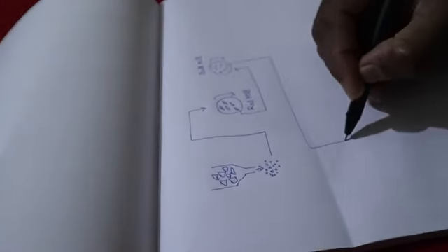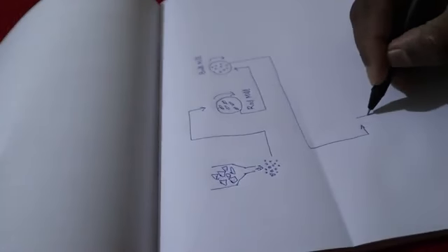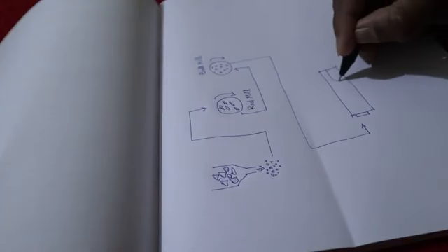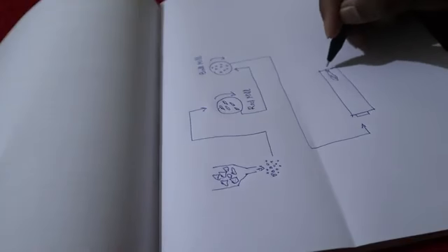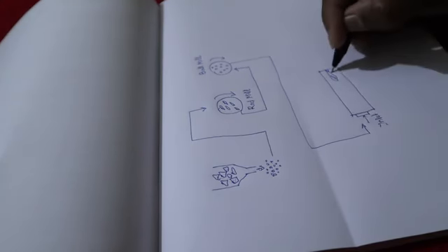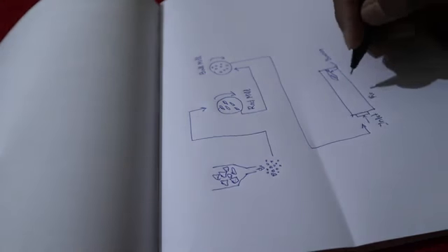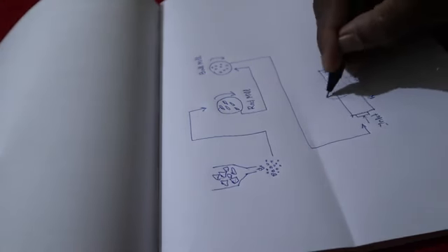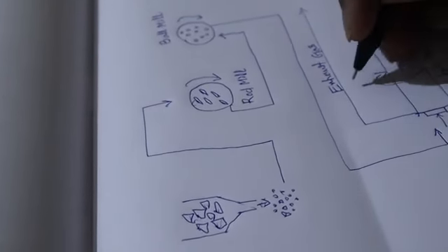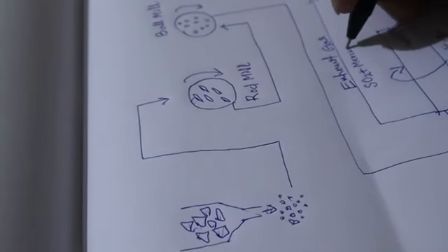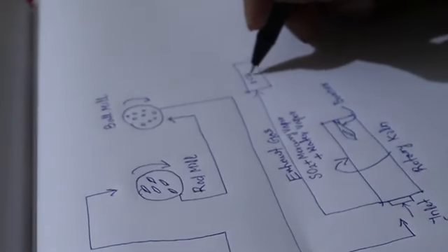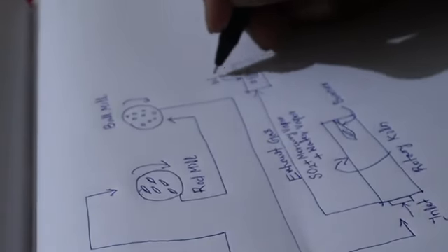Once the ore is finely powdered, it is fed into a furnace or kiln to be heated. The heated cinnabar reacts with oxygen in the air to produce sulfur dioxide, allowing the mercury to rise as vapor. This process is called roasting. The mercury vapor rises through the exhaust along with sulfur dioxide and water vapor. The mixture of gases passes through a water-cooled condenser.